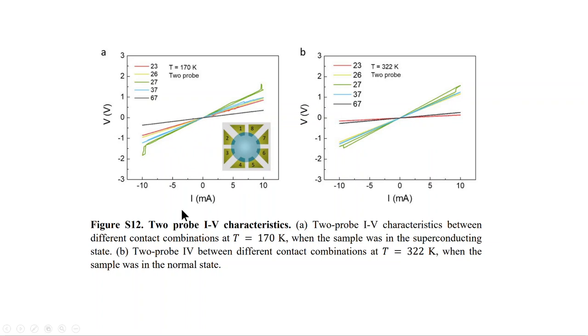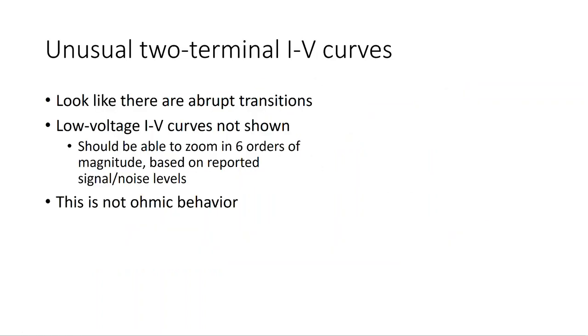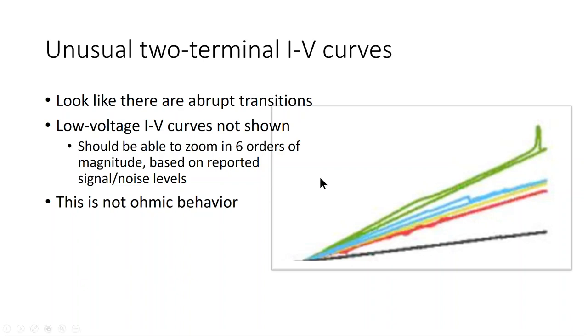If you look at these curves, though, and you look at them closely, what you'll see is that there are a number of abrupt transitions, in particular in the transitions for leads that are from one side of the sample to the other side. So this kind of thing here that you see, this jump here, the fact that there is hysteresis at all is a very alarming thing, right?